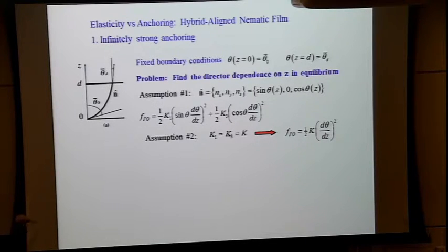Now, this liquid crystal has a boundary beneath it being glycerol or water, and you would expect that the surface easy axis, the orientation that is imposed by the interaction between the molecules here, would be something, and that something experimentally is tangential. So the molecules of most liquid crystals prefer to be parallel to the surface of water or glycerol, and this would be air, for example, a free surface. And again, experiments tell you that typically the molecules of liquid crystals prefer to be perpendicular to this interface.